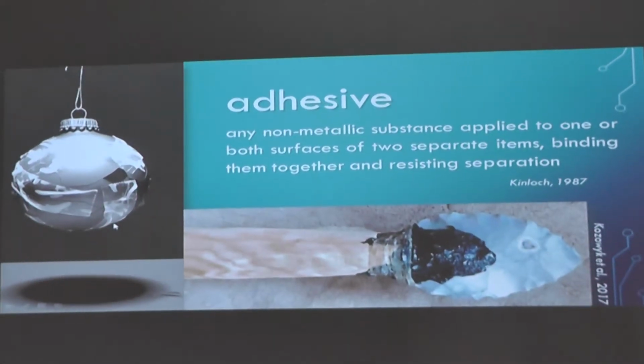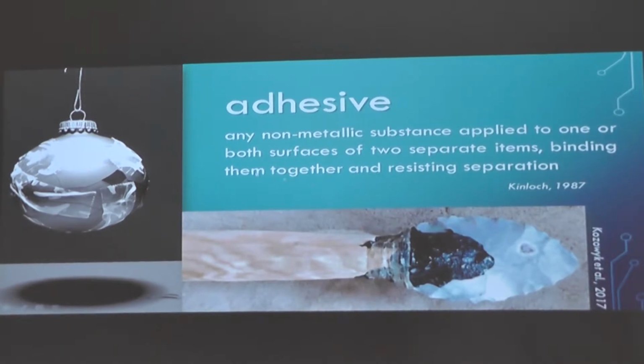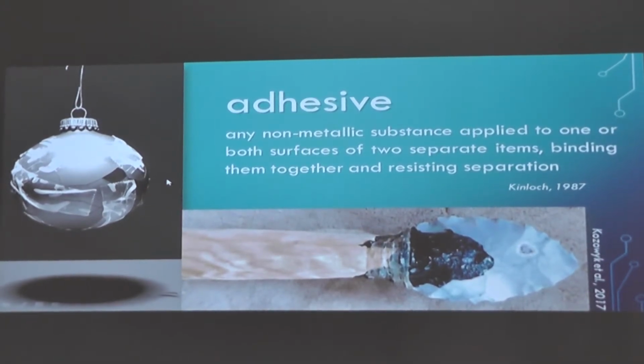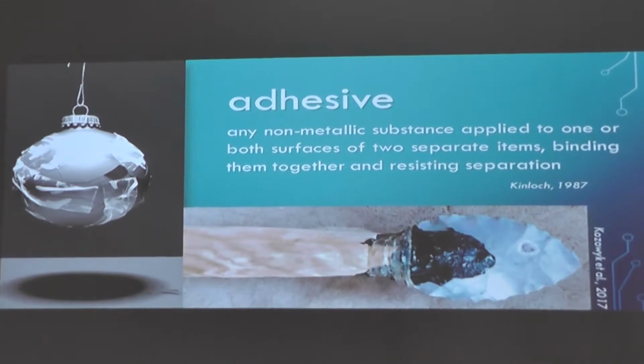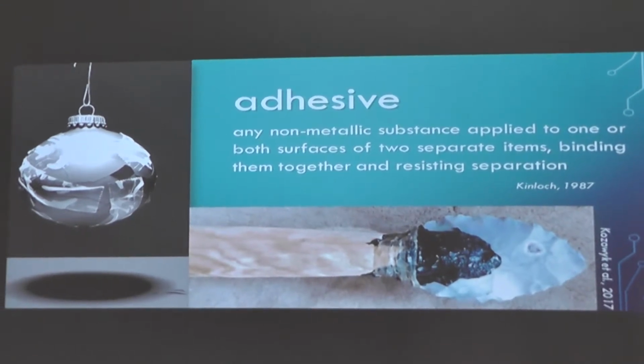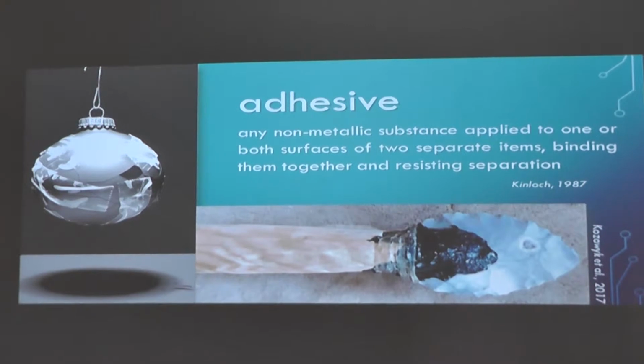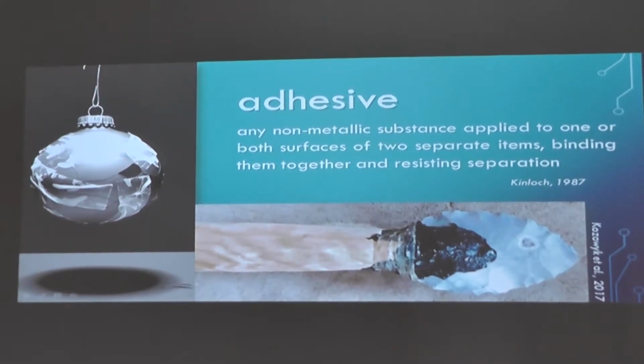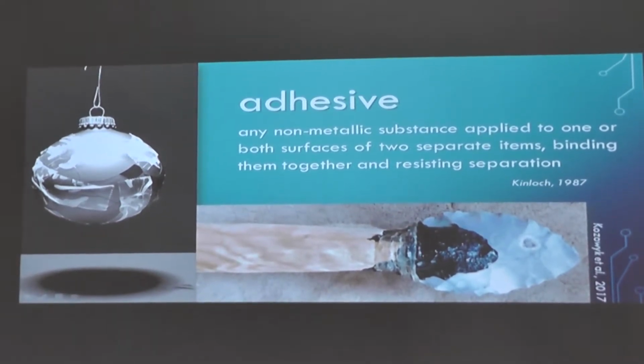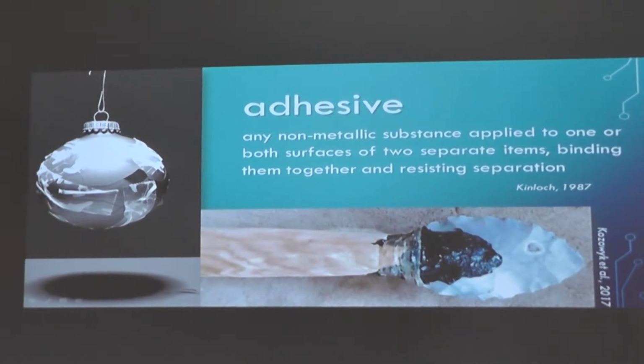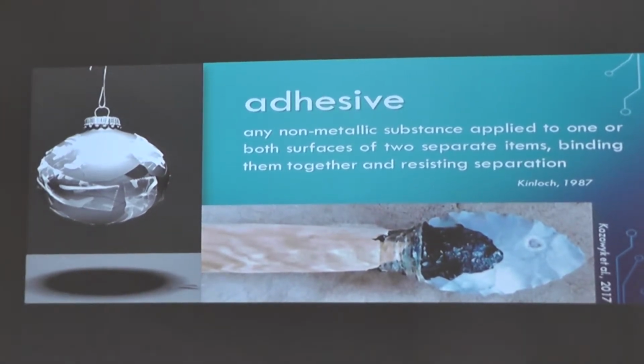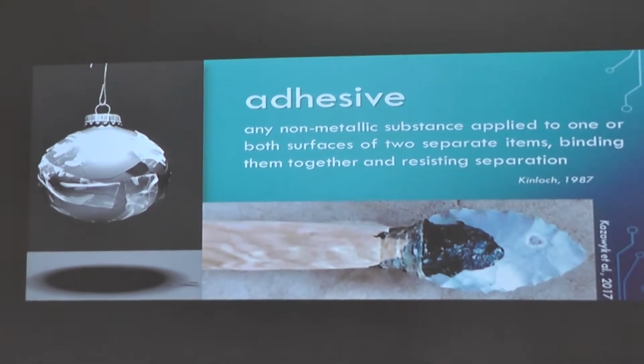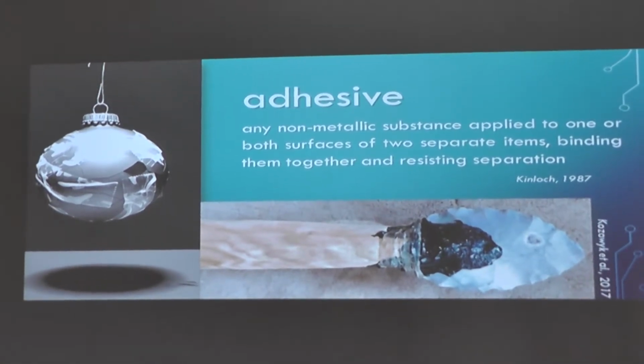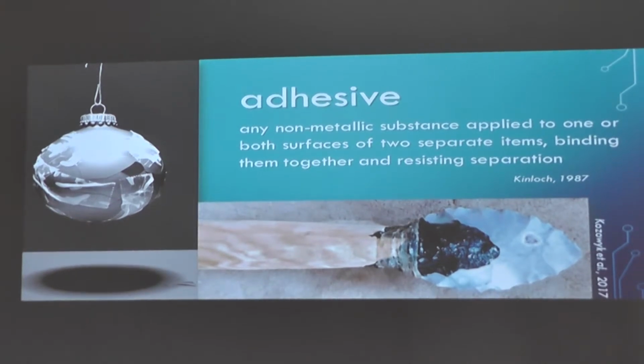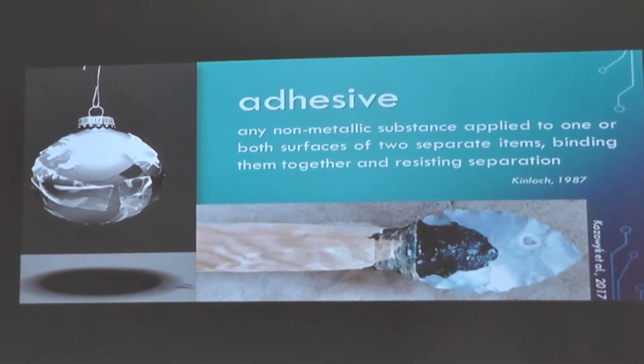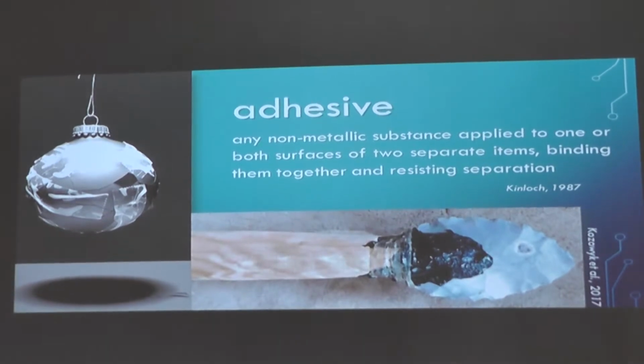This is a modern invention, and all the adhesives throughout history were always of natural origin. Only within the last 100 years synthetic materials have been developed, and also synthetic adhesives. And what is interesting is that this is a celluloid tape that is on one side covered with a very small layer of methyl methacrylates, which are actually the same materials that we use in our bonding.